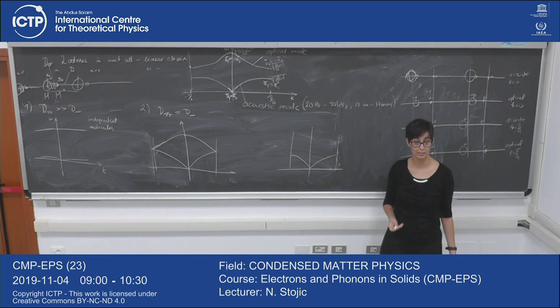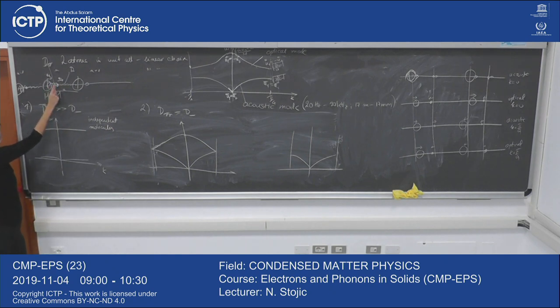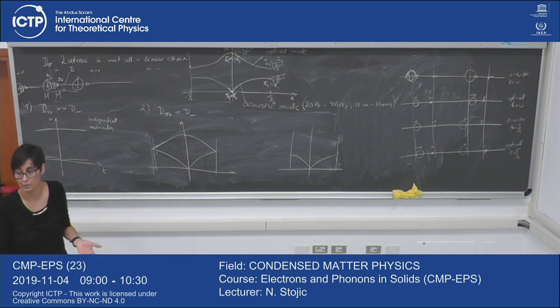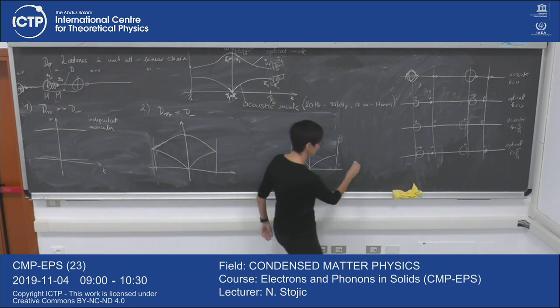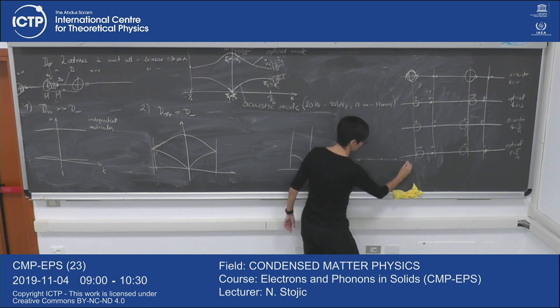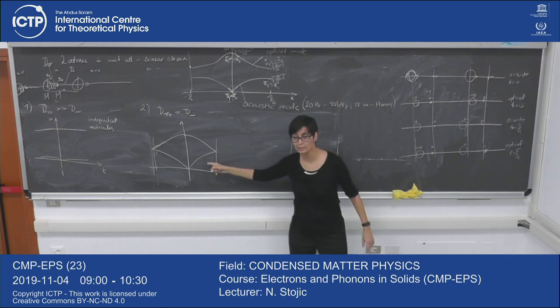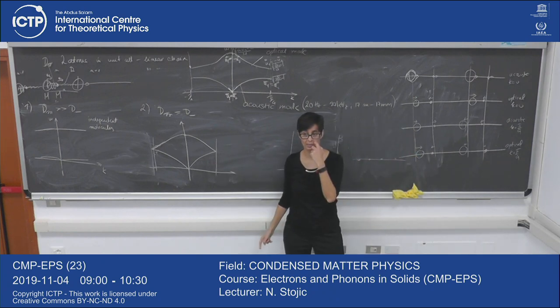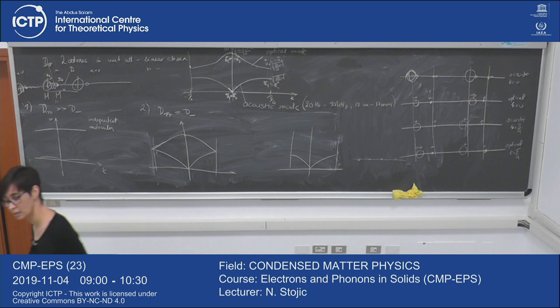You understand? Because in this limit, you're making them equal, and the masses are equal. So there is nothing to make one different from another. So it is just the case we had last time of identical atoms, monatomic, in a chain. Last time we got this sine square k half, now we're getting this. I think the top one is the contribution from the other atom. But they're the same, so the Brillouin zone has to be changed.